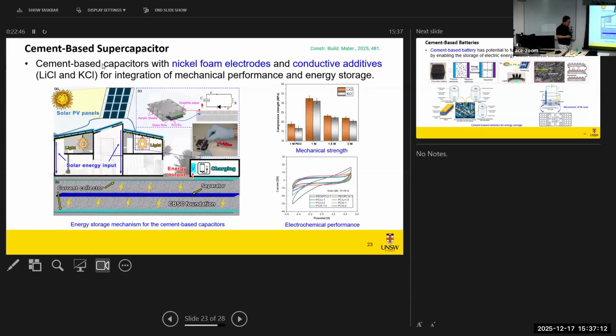So here we look at the effect of lithium chloride and potassium chloride as electrolytes on the electrochemical performance of the concrete capacitors. Basically, we found both of them can improve the electrochemical properties of concrete capacitors. For example, 1.5 mole per liter lithium chloride can give us the optimal capacitance. At the same time, 2 mole per liter potassium chloride can provide optimal mechanical strength and ionic conductivity.